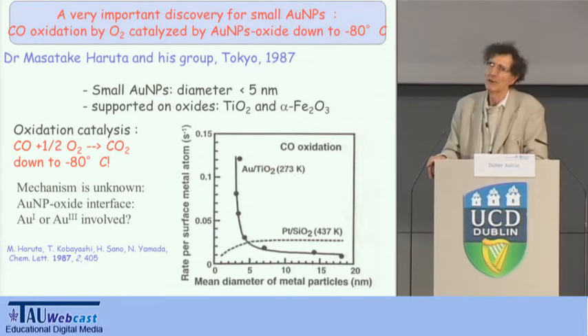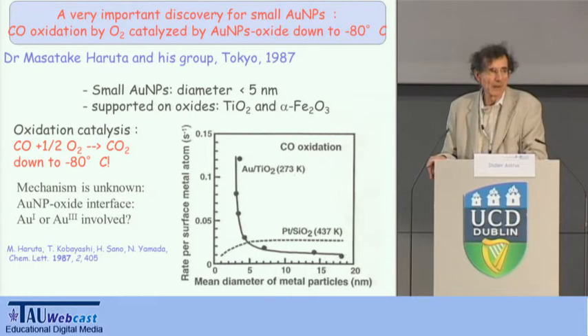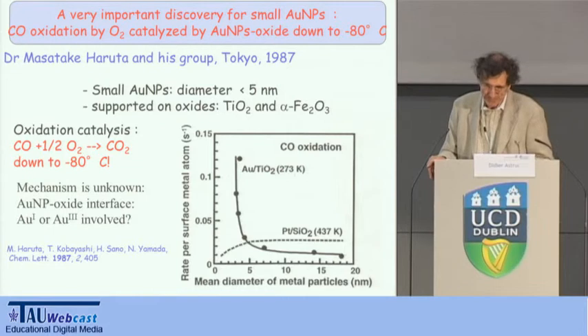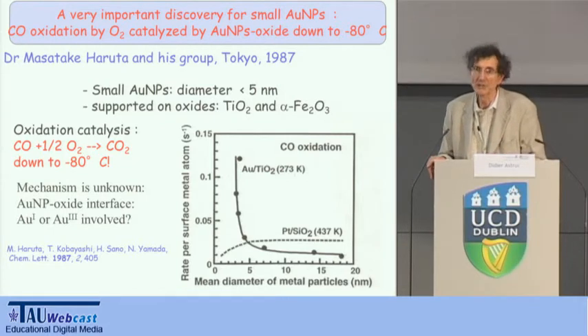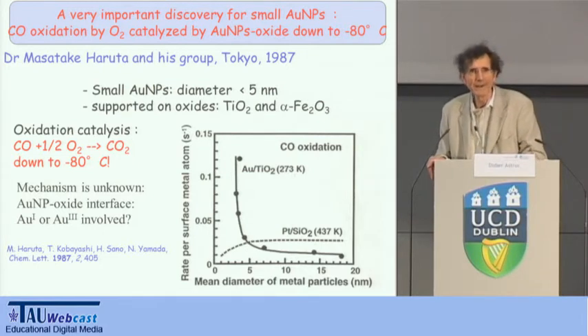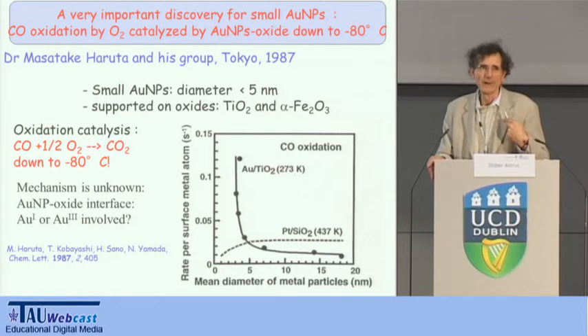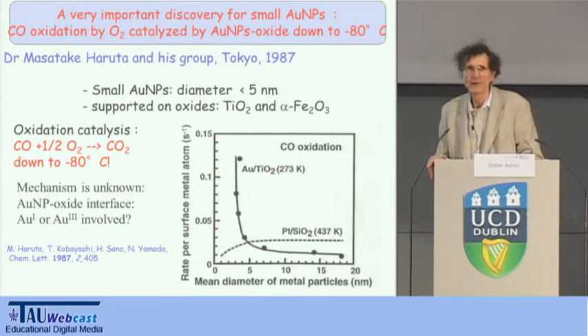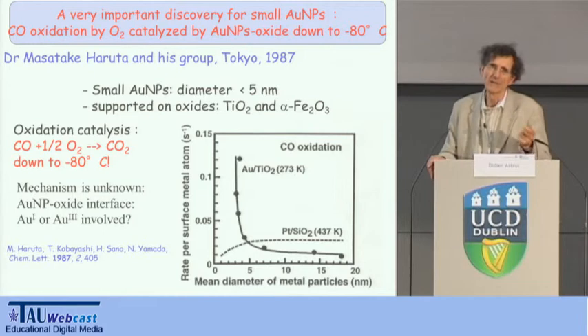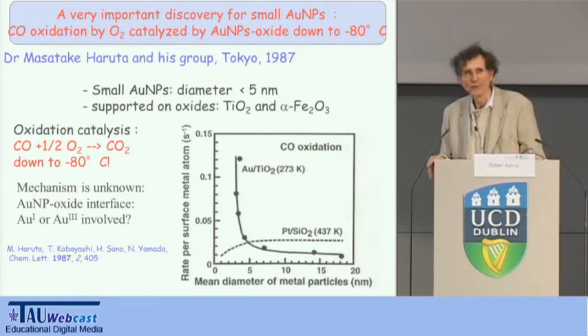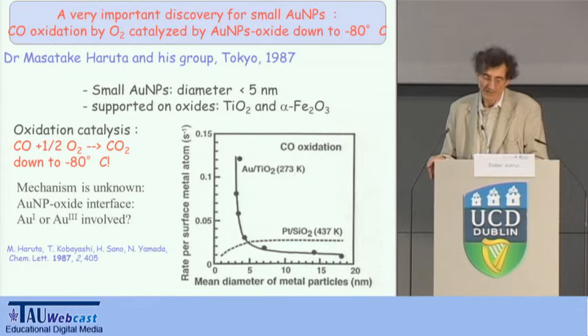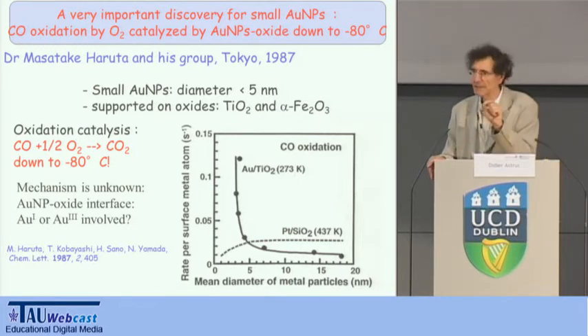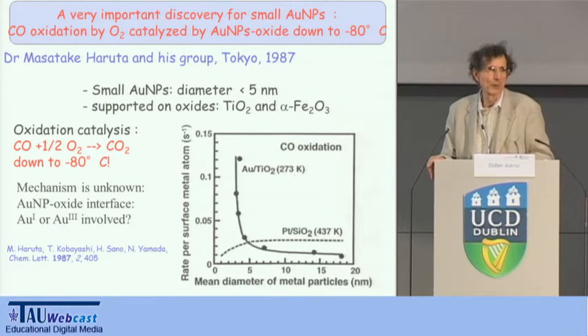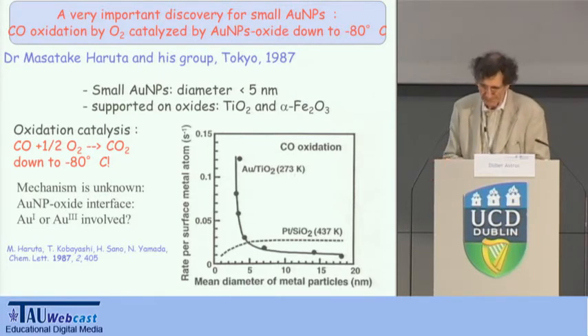And catalysis deals not only with oxidation, but also a number of reactions which have been discovered in the last quarter of a century. So this means that gold nanoparticles now are going to be increasingly used in catalysis. You can see the production in terms of publications, which is becoming very high in the catalytic field. So these scientists will have to be concerned with the toxicity issues because they are always dealing with nanoparticles which are coated with oxide. And in this case, it is probable that at the interface between the gold and the oxide, you have gold 1 and gold 3, which are generated.